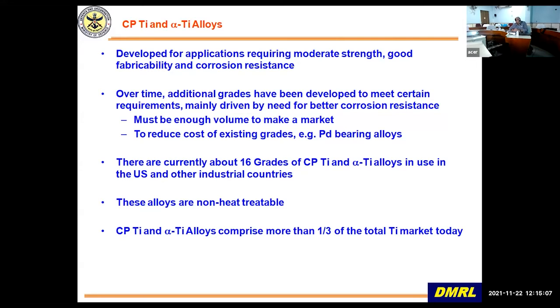Now, as far as the grades go, there are about 16 grades of commercial purity titanium and alpha titanium alloys in the US and other industrial countries. These alloys, the very fact these are single phase alloys, they are non-heat treatable. That is, you don't gain in strength by heat treating. So that is why they are called non-heat treatable. But certainly you can do stress relieving. This commercial purity titanium and alpha titanium alloys approximately comprises 1/3 of the total titanium market today.